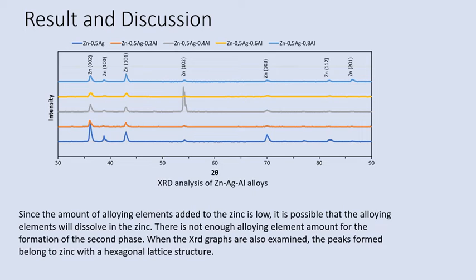And now we will talk about the results and discussion. What you're seeing here now is an XRD analysis, and I can say that the alloying amounts we use in this study are very low, and there is not enough alloying amount to create a second phase. As you can see from the peaks in the XRD graph, all the peaks belong to zinc, and there are no second phases.